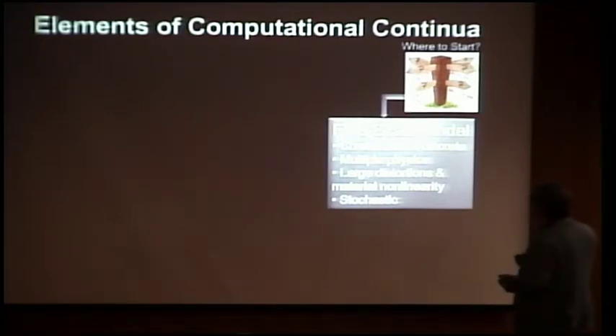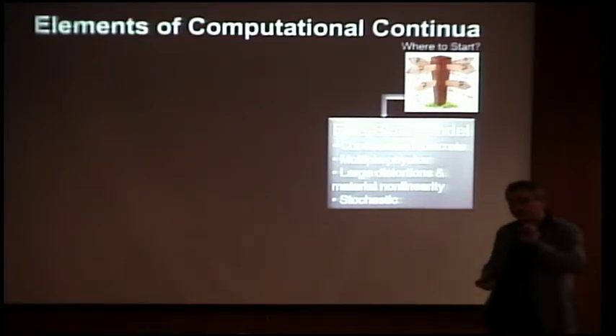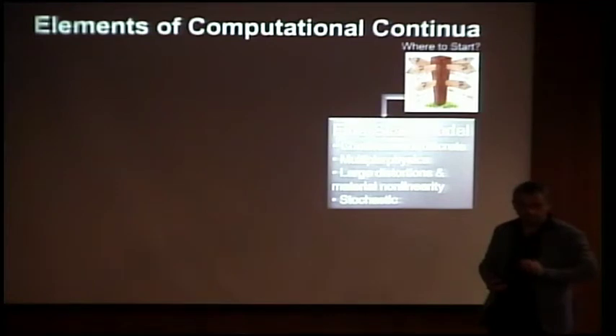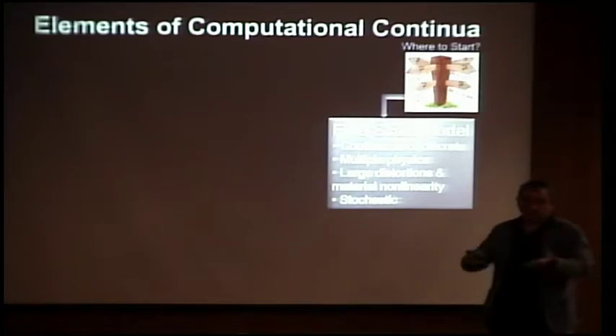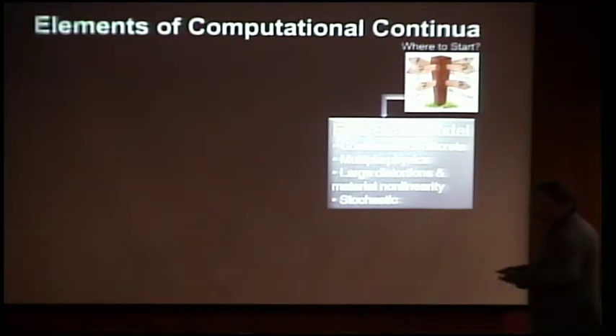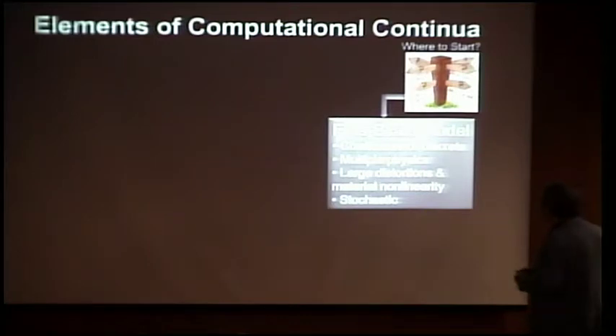Take polymer matrix composites — carbon mixed with polymer. We have experience of how carbon behaves, we know how the polymer behaves. If we then understand how to upscale that information all the way to the nonlinear regime, we can — with less characterization — characterize polymer, characterize carbon, and then by simulation predict how this thing will behave together. So we start from where we have the best understanding, with minimum uncertainty. The system can be continuous or discrete, represent multiple physics, large deformation, and must be characterized in a stochastic sense.